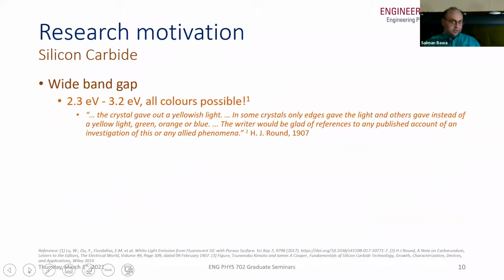So let us try to introduce silicon carbide, which is a wide band gap material. The band gap varies from about 2.3 to 3.2 electron volts, which means that all visible colors are possible if we are using silicon carbide. In fact, when silicon carbide was discovered by Henry Round in 1907, he mentioned observing several light colors: yellow, green, orange, brown, blue.